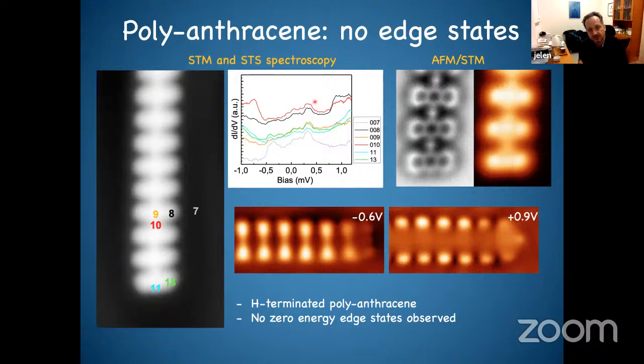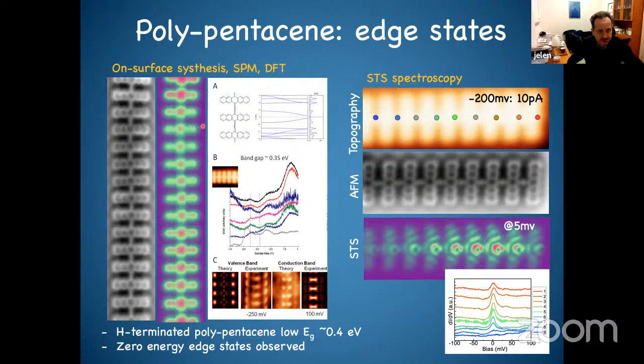Okay, so it means there is no edge state. And now the next step is, of course, we would like to have the same precursor, but in pentacene, which would already be in this topologically non-trivial state. So again, we use the precursor, which is very similar to the previous one, but instead of 3 benzenes, it has 5 rings. Now, again, you can grow it in the very same scenario as we did before, very long chains. And then again, the agreement between experiment and theory is good in terms of electronic structure. But importantly now, when we look at the end of the polymer, resolved by this chemical resolution, what you will find is that at the edge, at the zero bias, you will start to see very localized edge states, which are only living here. Okay, so it means that indeed we have a strong indication that this is changing the topology. Okay, now we are in a topologically non-trivial state.